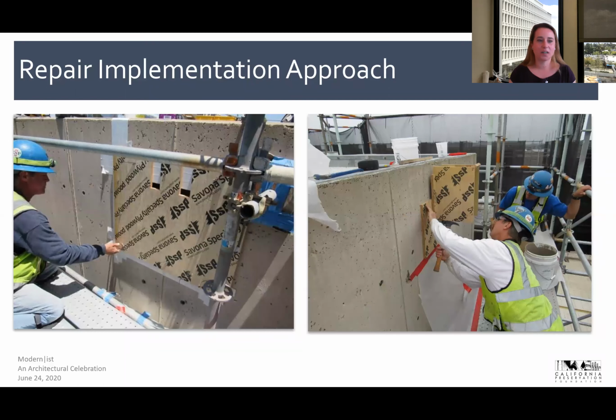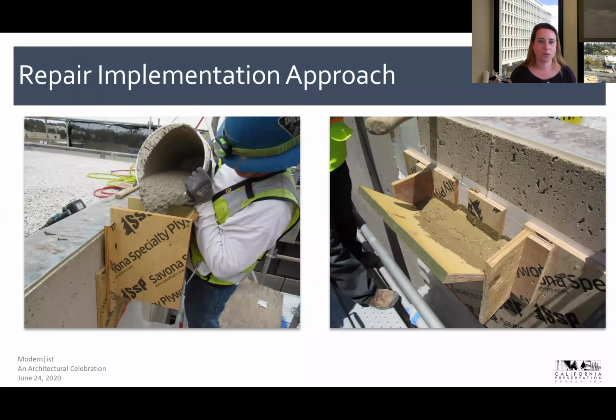With the formwork, you always have to have a way to get the material into the repair area. We call those bird mouths or spouts. You can see in the photo on the left the tiny little openings to get the material in. So understanding the constructability or flowability of the material and how it's going to be used during the mock-ups was really important in the development of our formwork. A spout was installed and you can see that on the right. And then the material was placed into the formwork. Again, all of this had been done in all of the trials and mock-ups.